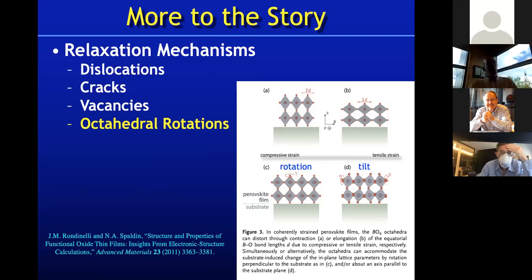In fact, many perovskites are famous for having these rotations. When the tolerance factor is equal to 1, that's when you should have a nice cubic perovskite with no octahedral rotations. But as the tolerance factor gets less than 1, that's where it becomes favorable to have the octahedra rotate, in the language that Antoine talked about. So you have a rotation around the c-axis. No, I misspoke.